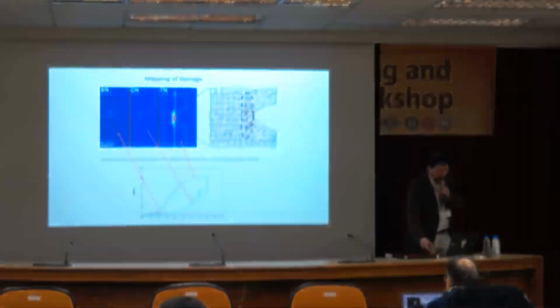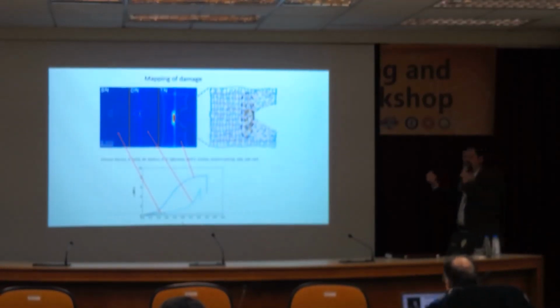The experiment has to be done completely in the dark. And all of this region here, which is 1 or 2 millimeter, is actually quite intense light emission, which is due to this bond breakage. Now, this is one particular material, which indeed is quite tough. If we do the same experiment for 3 different materials, this initial one in red was the initial network. The breakage is not detectable. So that means it's such a small scale that we cannot even detect the light emission. Of course, the sample does break, but we cannot detect it.